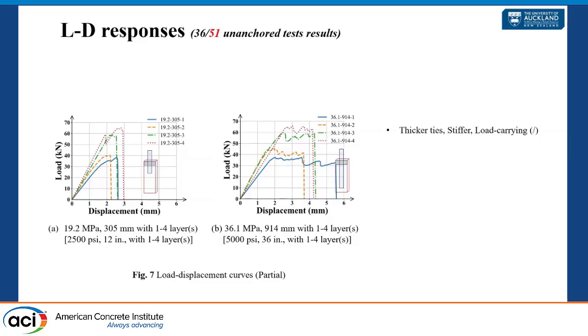The thicker, stiffer type always provides the higher load carrying capacity. And for the longer type, we find a longer plateau, serving as post-debonding deformation. And the third one is more intriguing, it's about concrete compressive strength. We just found that concrete compressive strength doesn't play a really significant role in our test. We assume that might be because we're using a really limited range of concrete compressive strength.